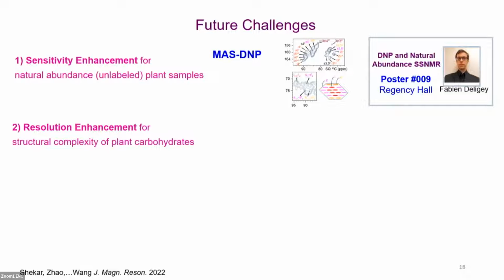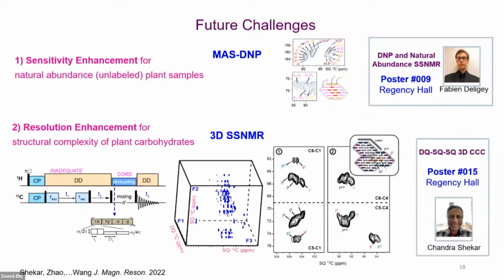So one solution is to increase the dimension of the NMR. Currently, we just developed a new 3D CCC experiment. We add the CORD block after the INADEQUATE, and we can get a double quantum to single quantum 3D spectrum. Here, it does increase the resolution of the carbohydrates. We can get a better interpretation of the cellulose polymorphic structure.